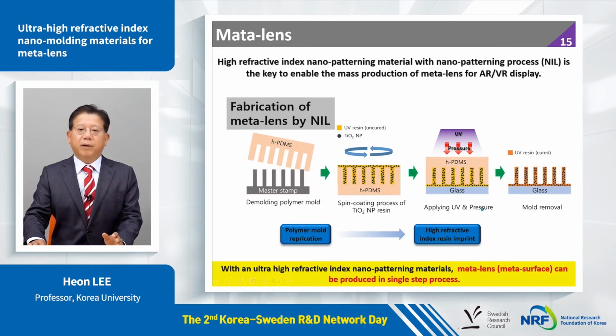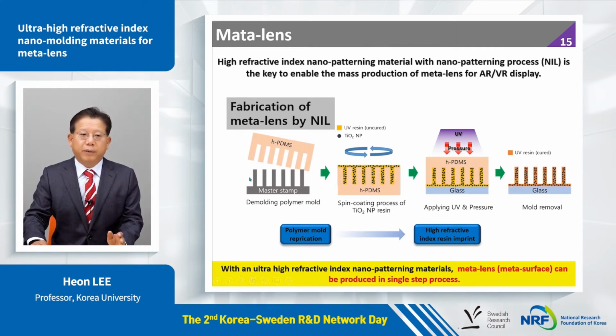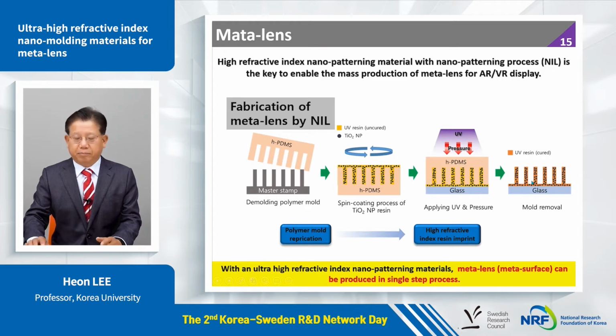And how can we make AR/VR display lenses? Well, what you need is a silicon master template. From this master template, you can make a polymer replica. On the polymer replica, you can apply high refractive index nanomolding materials, such as a mixture of UV resin and titanium oxide nanoparticles. Then imprinting gives us a metalens. It's a very simple, single-step process.